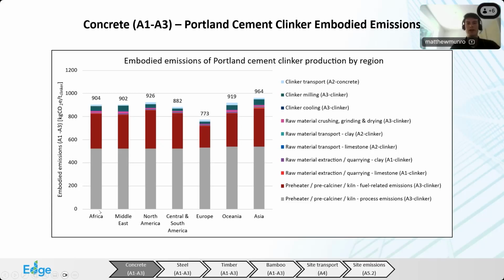But basically what this graph is showing is that for Portland cement clinker, most of these emissions are from the breakdown of limestone to lime that I talked about earlier. And then most of the rest come from fuels used to heat the material. So that's what you see here. And what you'll notice from this graph is that Europe has the estimated lower emissions clinker, and that's basically due to higher rates of both biogenic and waste fuels that are used to produce cement. Whereas in contrast, for example, Asia, based on the data we have, uses mostly coal and petroleum coke to produce clinker, and so that's why the emissions are higher.